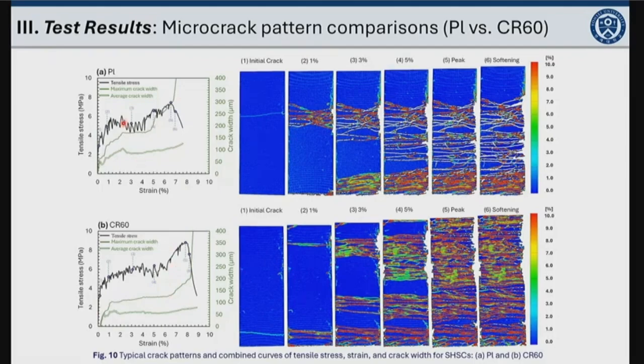For the case of the plain sample, the maximum crack width continuously increased in the strain hardening zone. But for the case of the CR60 sample, the increase of the maximum crack width was more effectively prevented, especially in the strain hardening. In addition, it was obvious that the CR60 sample produced fully saturated and much more microcracks at the peak point as compared to the plain sample.